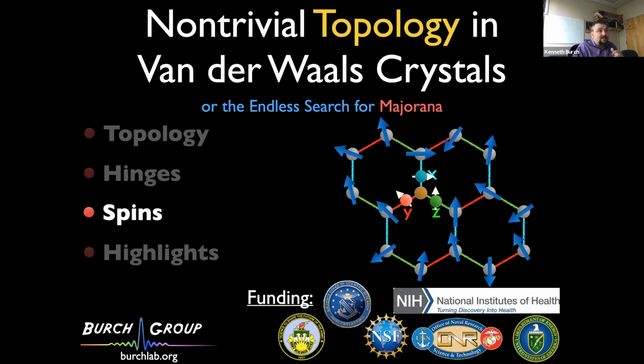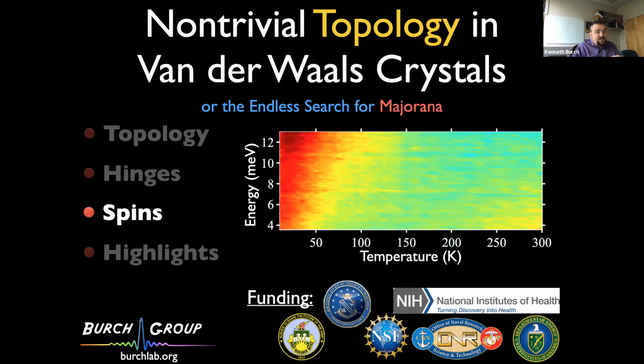But basically, it's an inelastic technique where you can measure the energy and temperature dependence. And what you're seeing here in color is the Raman response as a function, again, of energy and temperature, where red is enhanced and green is meant to be lower. Okay, and so you see this broad series of excitations, so you don't see anything well defined, but it exists up to fairly high temperatures, up to about 100 Kelvin. But what's interesting is if you look at the statistics, you can basically entirely explain the energy and temperature dependence just by using Fermi statistics. So these contour lines here are the predictions of what you would see with standard fermions. And so we take this as pretty strong evidence that indeed you do have these fractional excitations. And as I'll show you, surprisingly, they follow fairly well the pure Kitaev model. But we can also see evidence for where the non-Kitaev terms come in and so on.